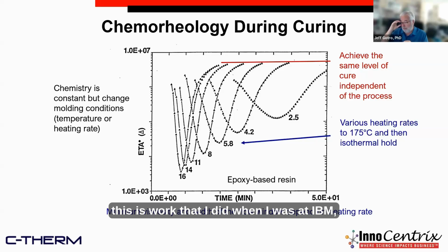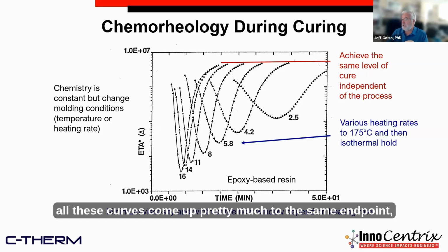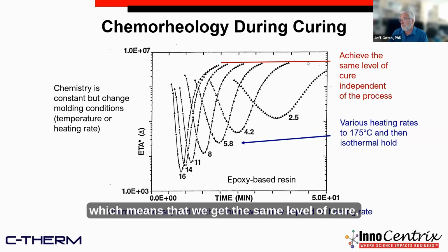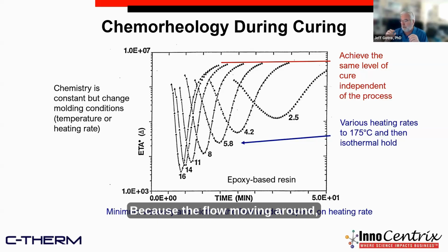In this case, this is work that I did when I was at IBM, and we developed a process that worked between 8 and 5.8, right here in the middle. So we had a nice, decent flow window, so the resin would flow, we could get it where we wanted it, and then it would fully cure. You can see all these curves come up pretty much to the same endpoint, which means we get the same level of cure independent of how fast or slow we move it around. The flow, the rheology, is governed by the thermal transients, the heat transfer, and the level of cure is driven by the chemistry. That's why we call this chemorheology: we modify the chemistry, and then we modify the thermal to get the right kind of flow.